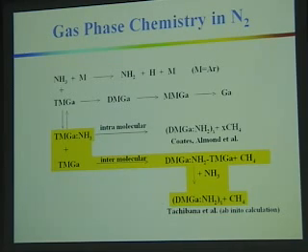The problem with trimethylgallium and ammonia, and our difficulty prior to 1992 of being able to achieve MOCVD of high quality gallium nitride, was the fact that trimethylgallium will form an adduct with ammonia. And this adduct then can further polymerize to form an oligomer. This oligomer will essentially take the gallium out of the reaction. The oligomer can form by an intermolecular mechanism.